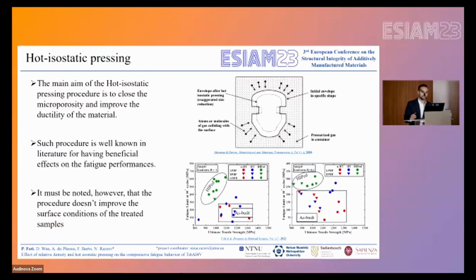Among all the post-processing techniques that can be used, we focus in particular on hot isostatic pressing that, as we can see from these diagrams that are reported here, is well documented to improve the fatigue performance of additive manufactured material. But as we all know, it's also limited. It has its beneficial effects when we have porosity inside our components, while this procedure doesn't improve the surface condition of the treated samples.